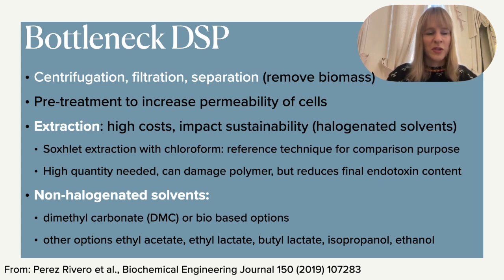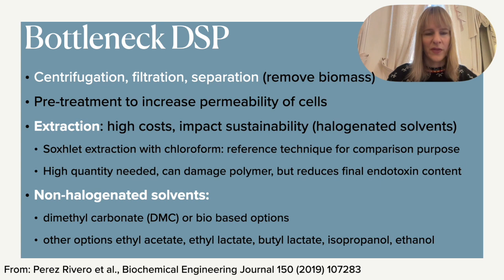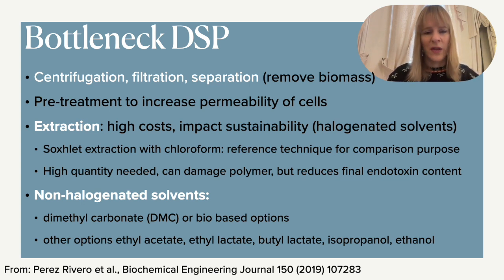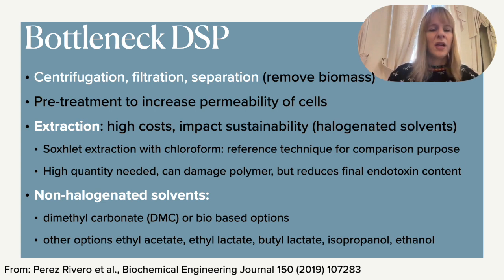Originally, people used Soxhlet extraction — extracting material from a powder using different solvents in a very specific setup — typically with chloroform, which is obviously a halogenated solvent. This is still commonly used as a reference technique, but it requires large quantities of chloroform, can damage the polymer, and has a sustainability impact. However, it is useful because it reduces endotoxin content. In order to move to more sustainable processes, people want to shift to non-halogenated solvents, such as dimethyl carbonate or other bio-based options including ethanol.